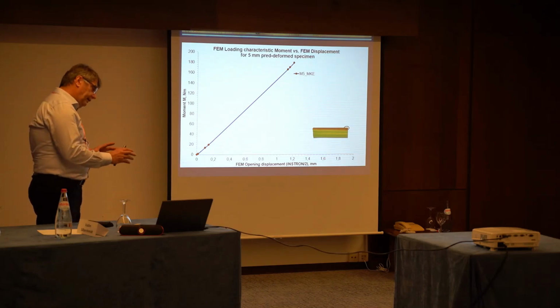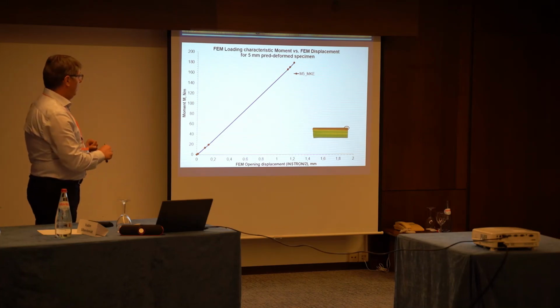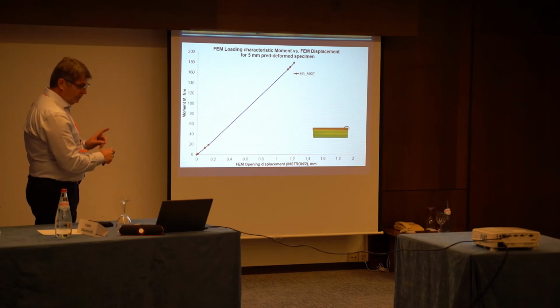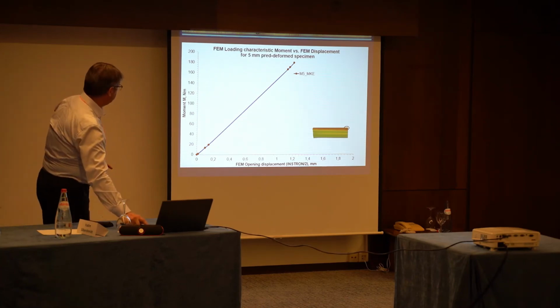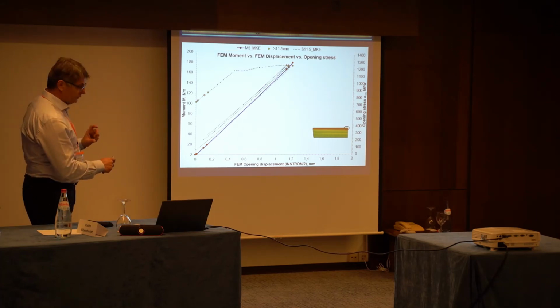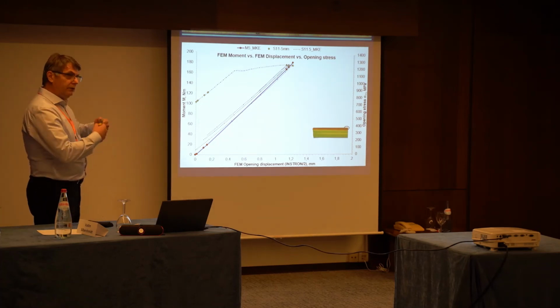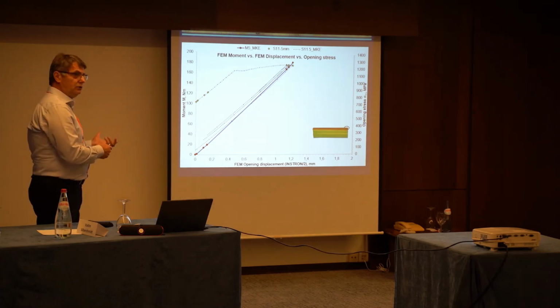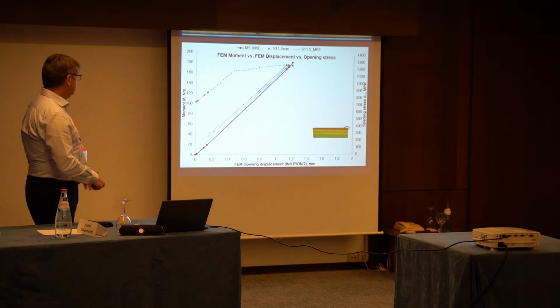So this is combining material properties with the finite element computation in order to determine the behavior of loading, to determine the loading amplitude. Because amplitude is not what we assume will be just a simple calculation, but it depends on the behavior of the material. So here we have the stress on this side, opening stress, and here we have the moment.